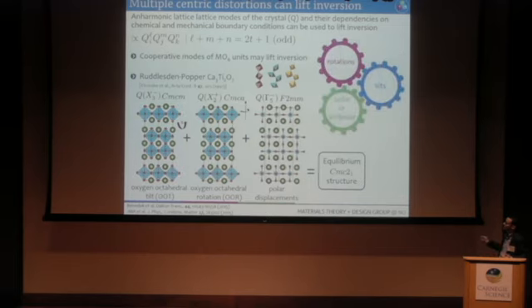Okay, and the idea is quite simple, that you have multiple modes that are coupled to each other, and they interact, and they lift inversion symmetry. Nothing I described here relies on the chemistry other than that the cations are of a particular size to favor these types of centrosymmetric distortions. Tuning the size and the chemistry can increase the polarization, but that's a secondary consideration, at least in my mind at the moment.